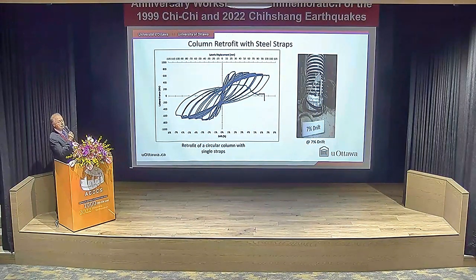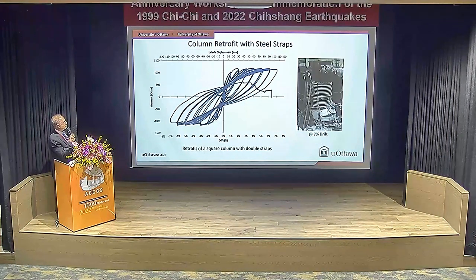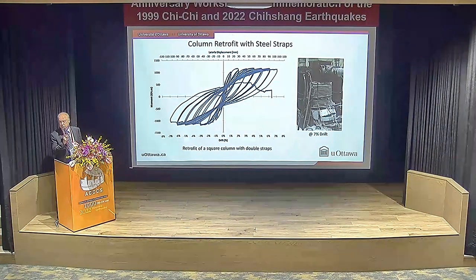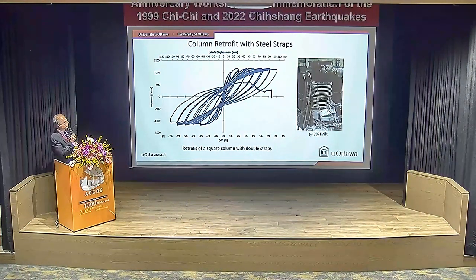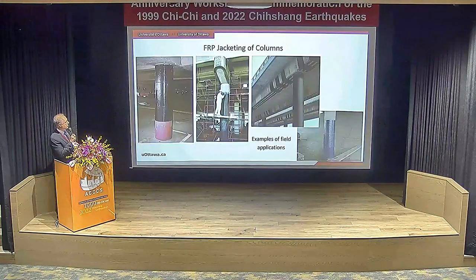And here you see the behavior as compared to 2% drift capacity in the non-retrofitted column. Now we were able to go up to 5, even 6% drift in this column. And this is the failure at 7% drift. And this is a square column which had shear deficiency, and one layer was not enough. We doubled the strips, and we again went as far as 6% drift before they started rupturing.